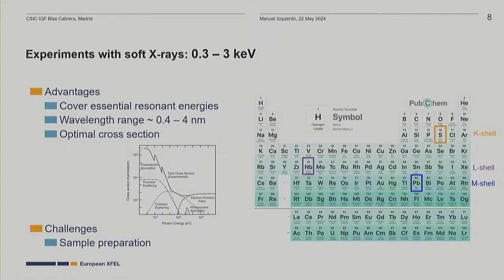A second advantage is that the wavelength is in the order of 0.4 to 4 nanometers, so it's ideal to study nanomaterials. The cross-section is also optimal because the photoelectric effect is going to dominate up to around 12 kiloelectron volts, and from there on other effects come into play. This means that the light-matter interaction process is going to be very efficient.